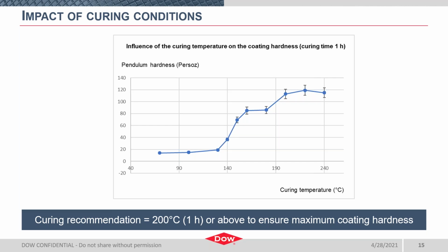Up to 130 degrees Celsius, we see relatively no curing is taking place, and the film hardness remains low. We don't see that hardness development really start trending upward until we get to 130 to 160 degrees. And then, of course, we look for that point where we see a plateau, the point of diminishing returns, around 200 C. So this is going to be the genesis for our oven cure recommendation.